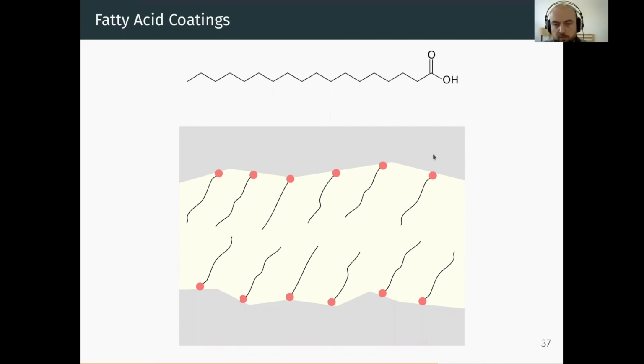So what you typically do is you have a solution of a fatty acid such as this molecule, you spread it across your surface, and what happens is that this hydrophilic group tends to bind to the surface. And the molecules self-assemble into a monolayer. There's typically only one molecule thickness on top of the surface where the molecules bind. And the interaction between the tails of those molecules is what gives the decrease of the friction coefficient.